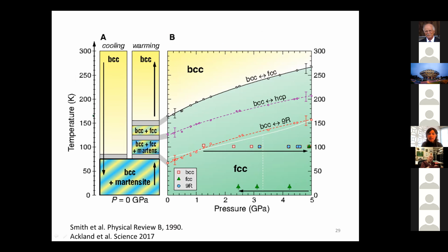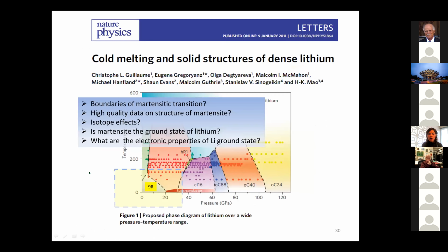This is an early study showing that even though during cooling we were going from BCC to this Martensite, when we warm up, we recover some of the FCC. That was a smoking gun telling people that maybe this FCC is in fact a stable phase, and the Martensitic transition happens for some other reason. There are kinetic effects involved. So we looked at this region. We wanted to find these boundaries because they weren't studied, and we also wanted to understand the isotope effect in them, because that's what we thought was originating these problems.